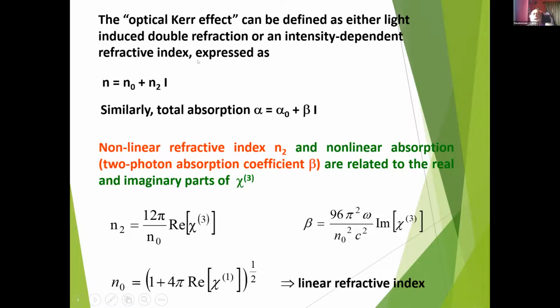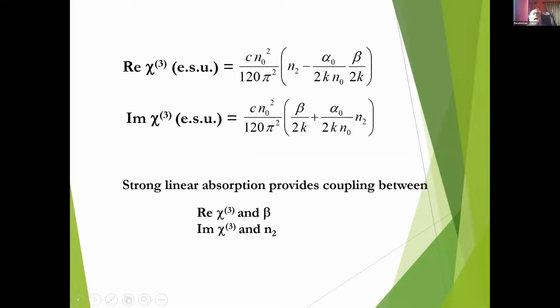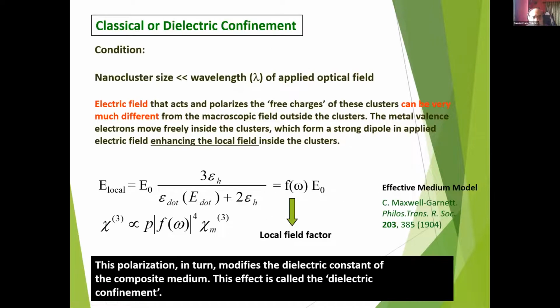Now, as I mentioned, n equals n naught plus n2 I, where n2 is the nonlinear optical refractive index, which is a function of the third order susceptibility. So it is a function of the real part of chi3, because chi3 has two components: a real part and an imaginary part. Similarly, you also have the absorption coefficient beta, which is related to the imaginary part of chi3. The detailed expressions are modified if a strong linear absorption provides a coupling between the real part and the imaginary part of chi3, that is, between n2 and beta. Now, this is the main thing we are applying.